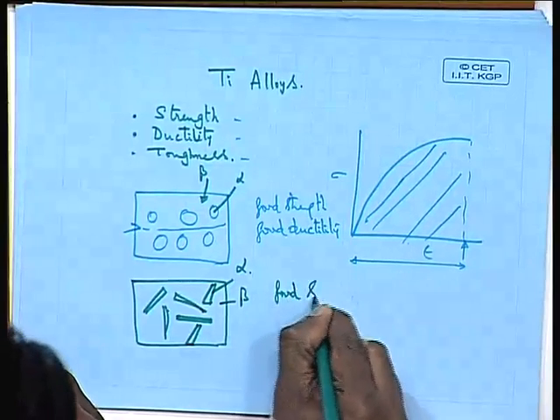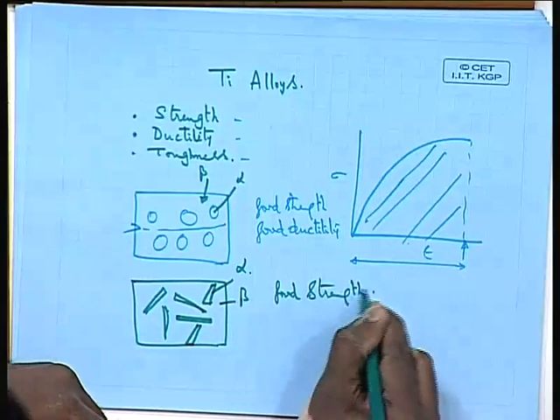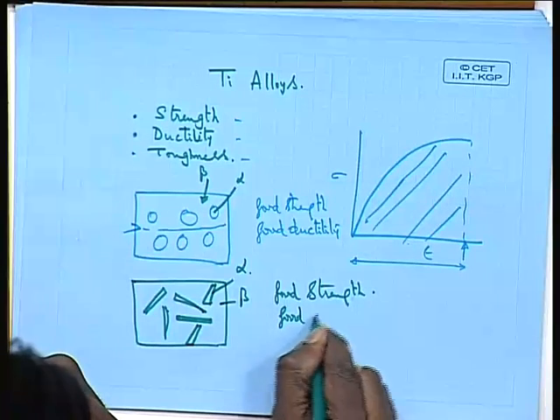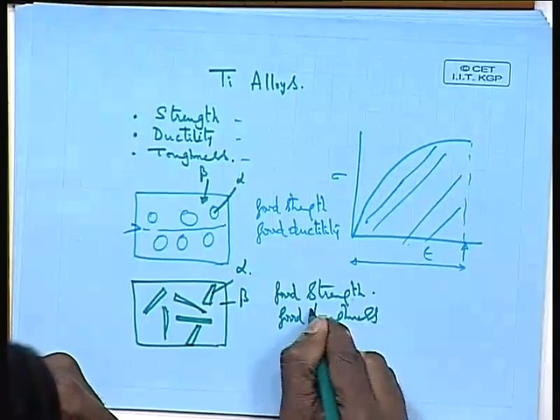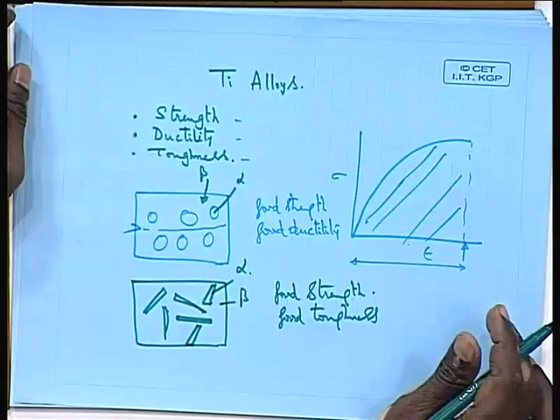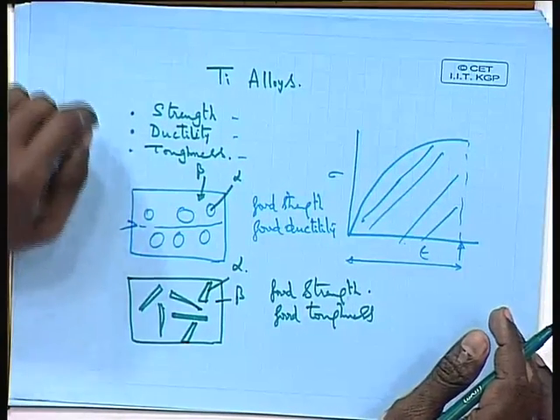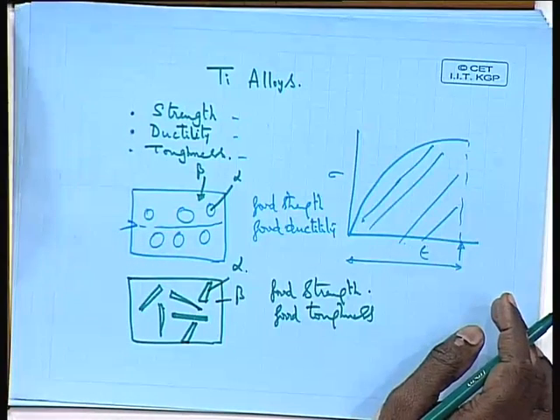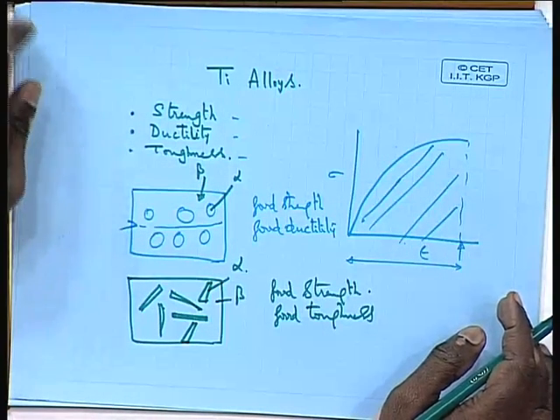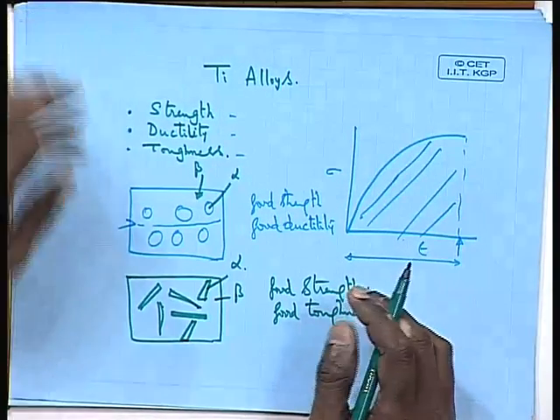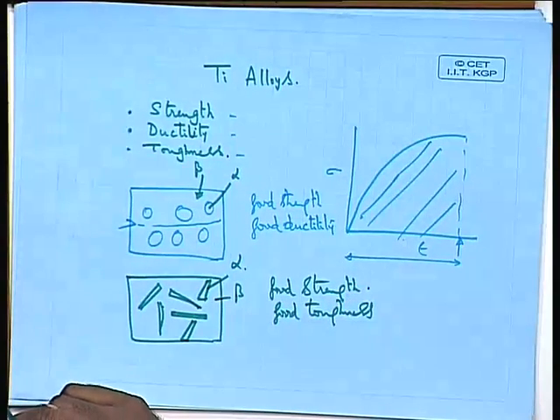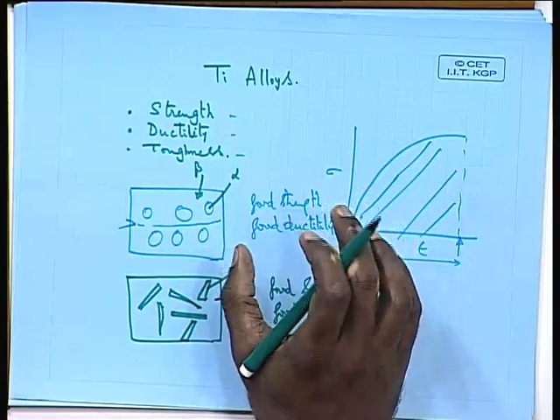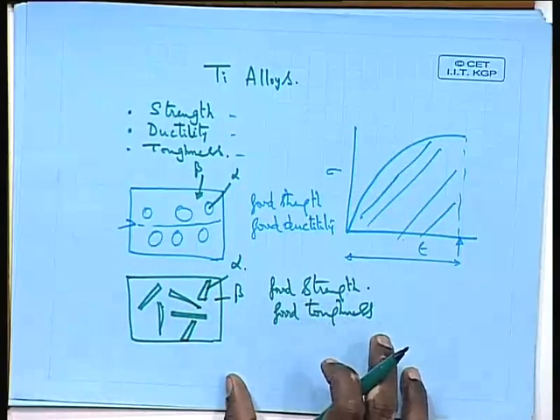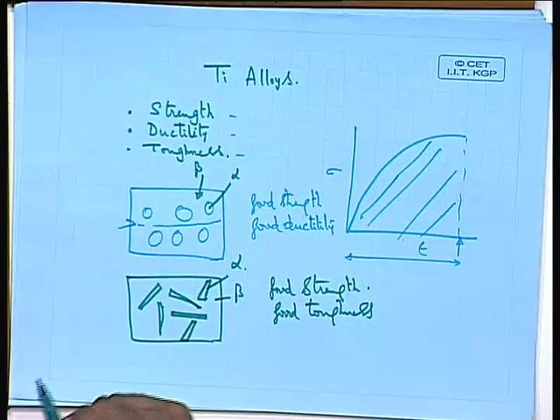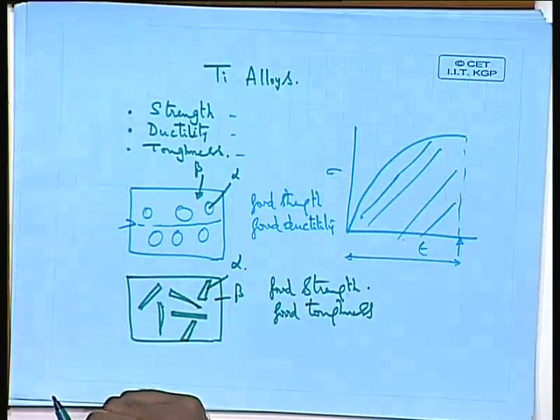good strength, no doubt, and it will have good toughness, but it will have poor ductility. The ductility of this alloy will be very poor. So as a result, we can see that of these two different microstructures, one has good ductility, another has good toughness, and the two do not have both. The first microstructure does not have a good toughness and the second microstructure will not have a good ductility.